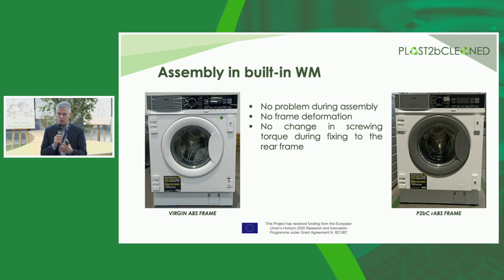You can see in those photos, on the left, the typical white frame, and on the right, the grayish, dark gray frame produced by using our Plast2bCleaned ABS. There was no problem in assembling that porthole. There was no deformation, confirmed. There was no problem in screwing that frame together with the back frame, and everything was fine. No change for assembly of this porthole.